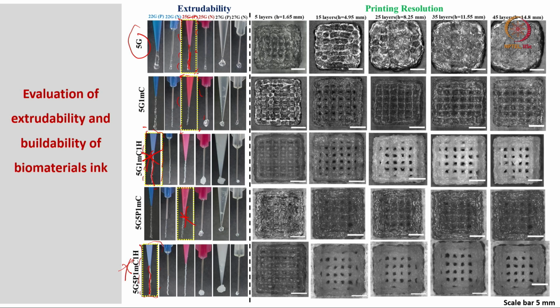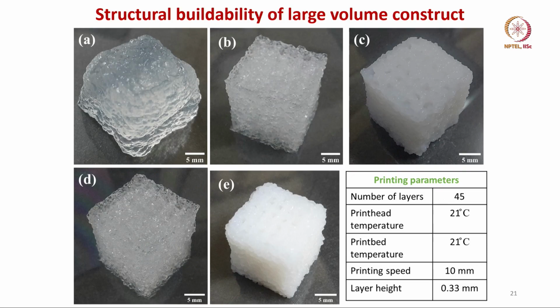Printing resolution wise, these are the as-printed scaffolds, and you can see the scale bar is 5 millimeter. With 45 layers, that is almost 15 millimeter, you can build the construct. And you can see structural buildability, you will agree with me that at a printing speed of 10 millimeter per second, at 21 degrees Celsius print bed and print head temperature, with 45 layers, this is the best.